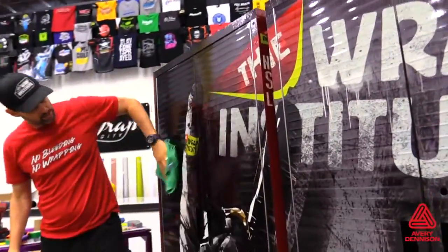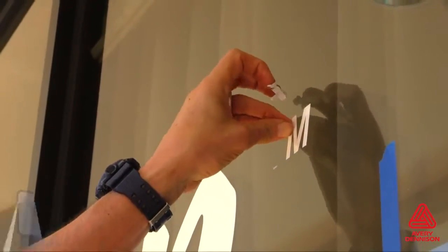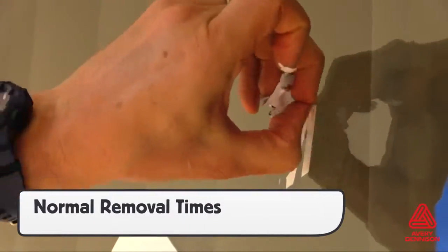Here are the removal details. All types of heat can be used to soften the film during the removal process. Always do so within the warranty period to get the best results. The permanent adhesive version of the V4000 will likely leave significant adhesive residue behind, while the LTR version leaves less than 20%. The LTR version will remove significantly better than traditional reflective films and can be scheduled like a normal full print removal using films like MPI-1105. Permanent adhesive versions will be more difficult to remove, requiring more time and use of adhesive removers, so be sure to schedule accordingly.